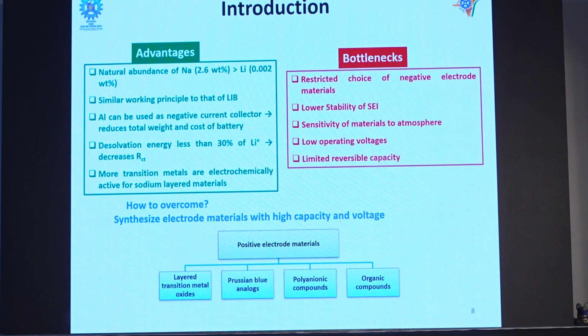What's a solid electrolyte interface? Normally in a lithium ion battery or any sodium ion battery, your electrolyte has a tendency to undergo parasitic reactions when the voltage increases past a certain limit. And if you have a very good electrolyte, or a component in the electrolyte, maybe an electrolyte additive, or even without an additive, some electrolytes will initially form a layer on top of the electrode surface by reacting with it. It's called a solid electrolyte interface.